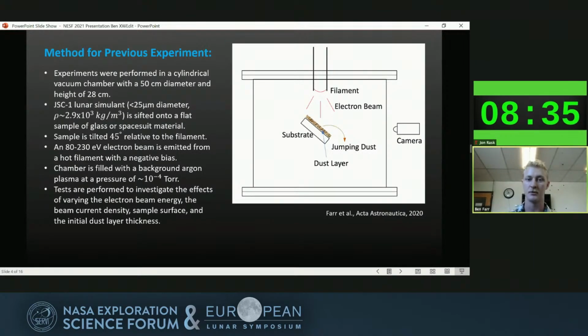In our experiment, we are using a hot tungsten filament to create an electron beam, and we are just shooting that beam at a dust-covered substrate. We've tested everything inside of a vacuum chamber where we feed in about 10 to the minus 4 torr of gas just to create a plasma background for the electrons to actually travel through.